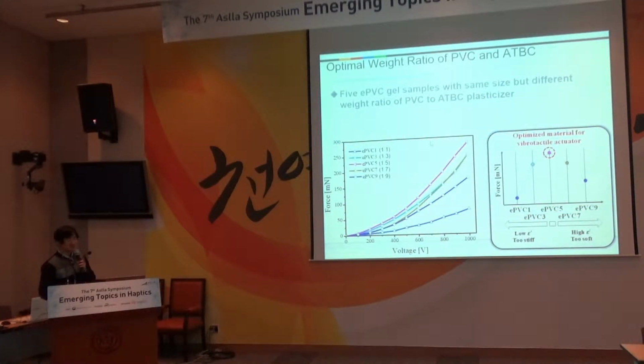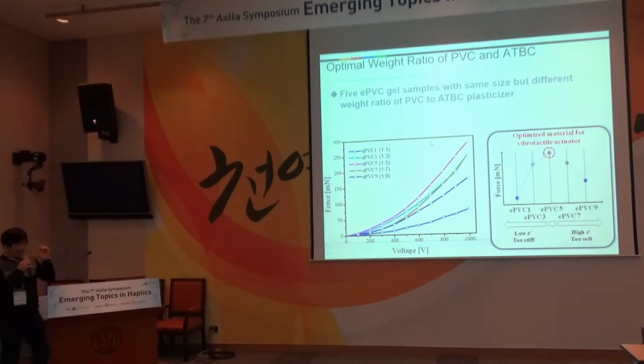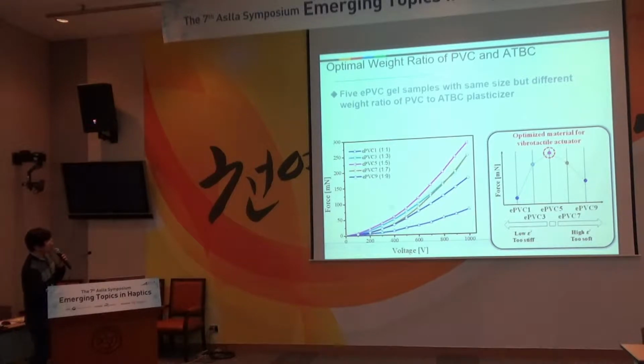And the weight ratio is another important factor. The dielectric property and mechanical property of the actuator depend on the weight ratio. So we prepared 5 ePVC samples with the same size but different weight ratios of PVC and ATBC plasticizer: 1:1, 1:3, 1:5, 1:7, and 1:9. So 1:5 has the best performance.